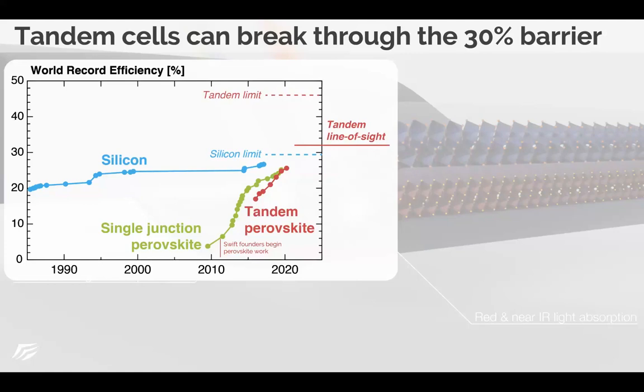So this is the exact same strategy that's been used successfully with other semiconductors, specifically III-V materials like gallium arsenide. And they've reached efficiencies as high as 39% with 6 junctions, but they also cost like $10,000 a square meter, so 100x more than silicon. And what the perovskites offer is the same kind of performance, maybe almost as good, at a cost that's actually lower than silicon, and that's a game changer.